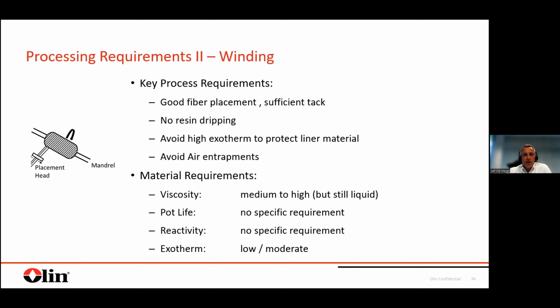Regarding the material requirements, the viscosity could be higher compared to the bath step, the impregnation step. So I would call it medium to high. For the pot life, in this step, you do not have specific requirements anymore. The winding itself is relatively fast, so you don't need a long pot life in this step. Regarding reactivity, it's more or less the same. And regarding exotherm, still you don't want to exceed the stability of your liner material.